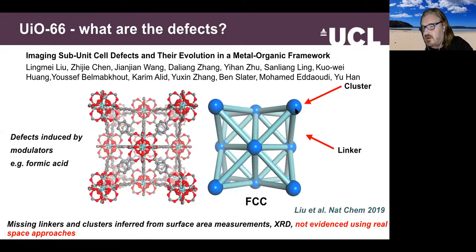So this is a material called UiO-66. What I want to draw your attention to are these things, which are polyoxymetallate clusters. In this case, they contain zirconium, and these are linked by this thing here, which again is a benzene dicarboxylate ring. So you can see there's two oxygen atoms there, which link to the metal, which is shown in blue. So schematically, we can think of this structure like this, and it happens to have an fcc, face-centred cubic type arrangement. So the clusters map onto these spheres, and the linkers represent these benzene dicarboxylate linkers.